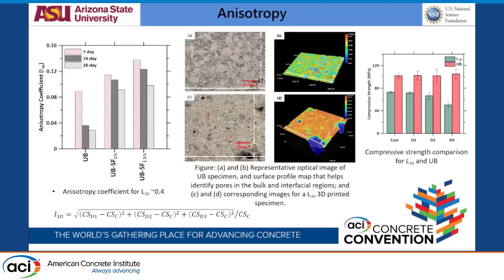Based on a microscopy image, the top two show a microscopy image for the UB mixture, while the bottom two images in the middle show a microscopy image for an L30 mix. That's our 70 MPa mix. So what did we observe? There were two major observations from the microscopy image. One, the lines that you see in the images that go horizontal are the interlayer joints, and the dotted lines that go vertical are the interfilament joints. If you see the UB mixtures, you will not really see large voids that are significant enough. But if you see the L30 mixture, we can see significant voids being formed along the interfilament and interlayer joints. Why does it happen like that?